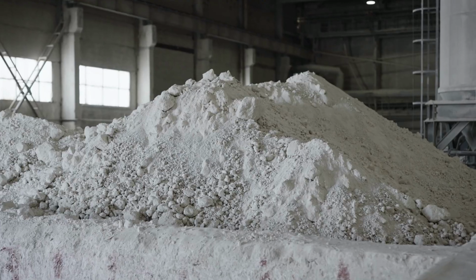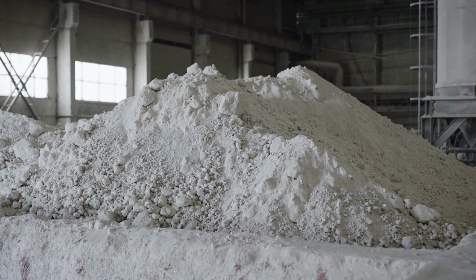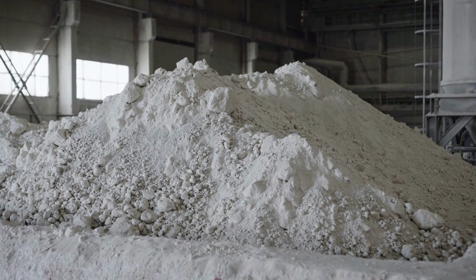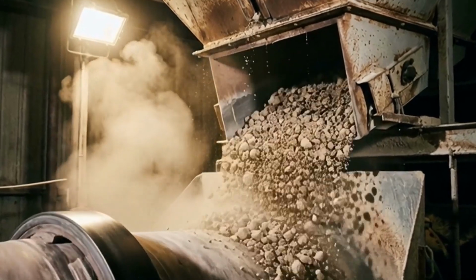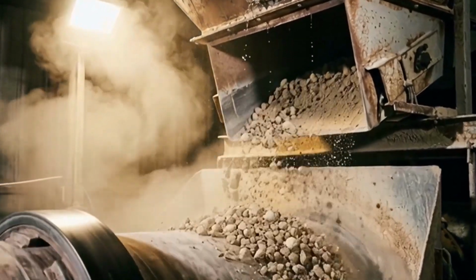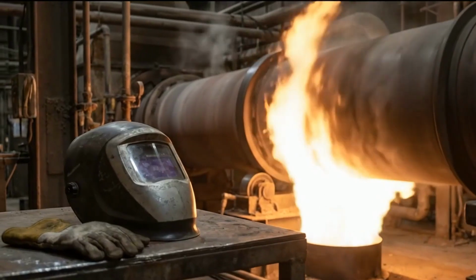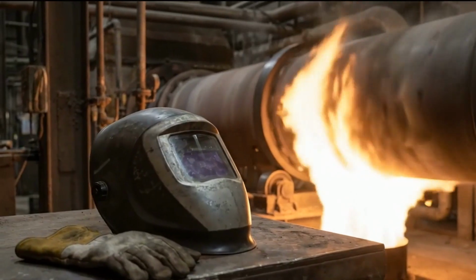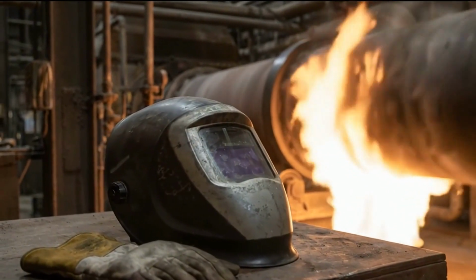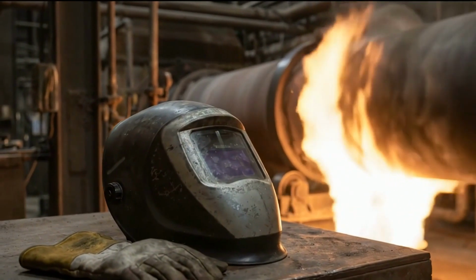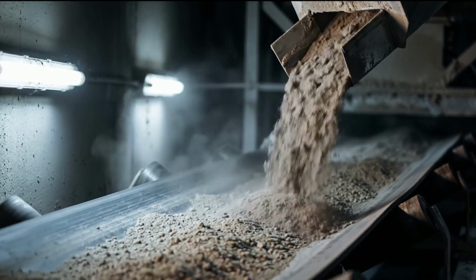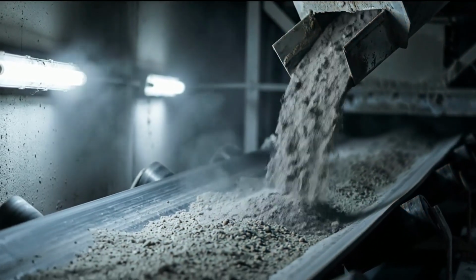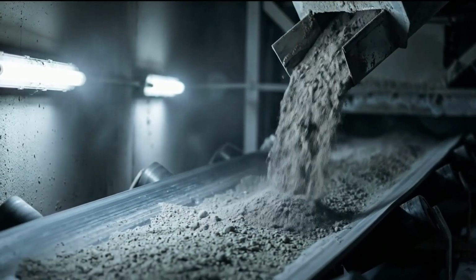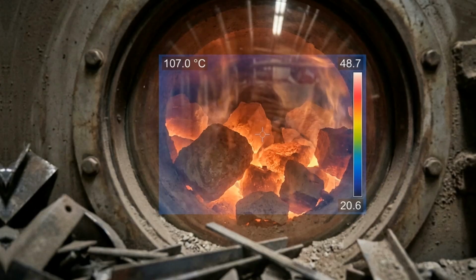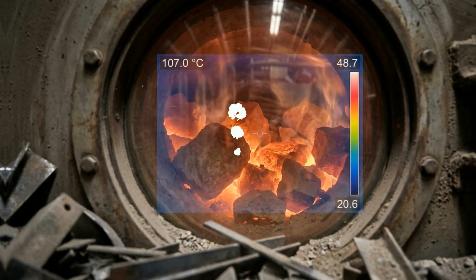Raw meal, a finely ground mixture of limestone, clay, and other minerals, is fed into the upper end of the kiln. Gravity and rotation carry it slowly down the length of the tube toward the burner at the lower end, where a flame fed by coal, gas, or alternative fuels produces the heat. The material spends roughly 30 to 40 minutes traveling through the kiln's full length, passing through progressively hotter zones as it goes. What happens chemically during that journey is the entire point.